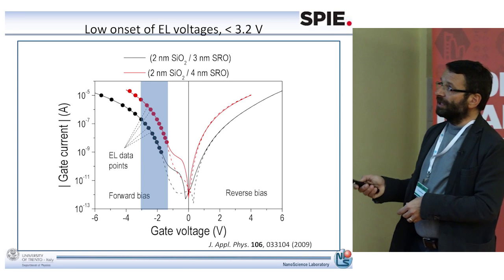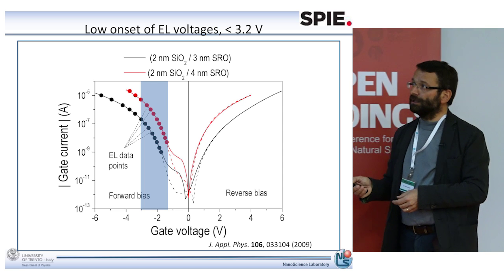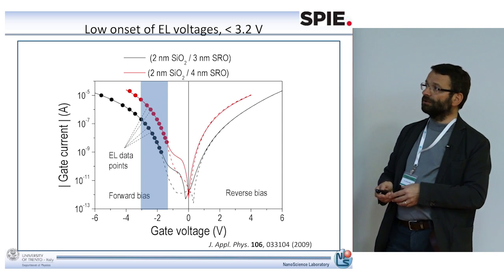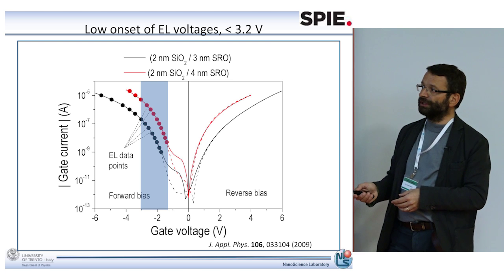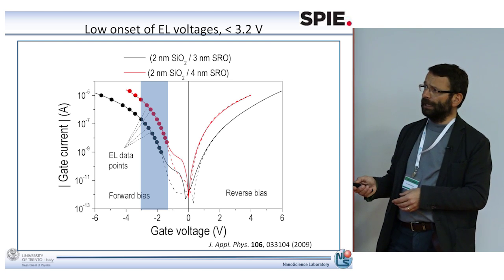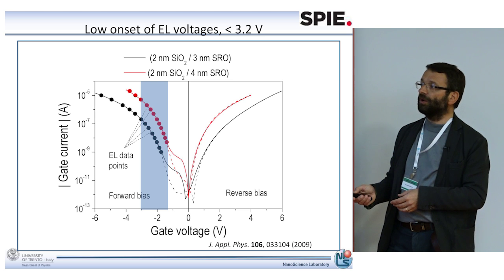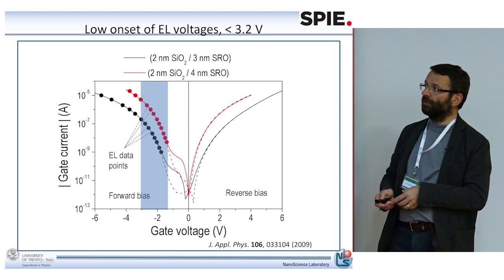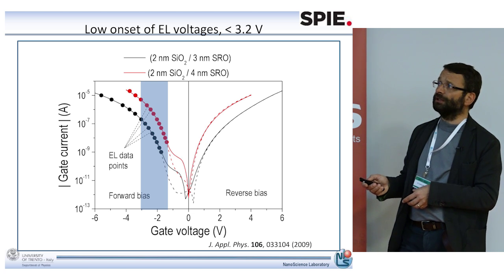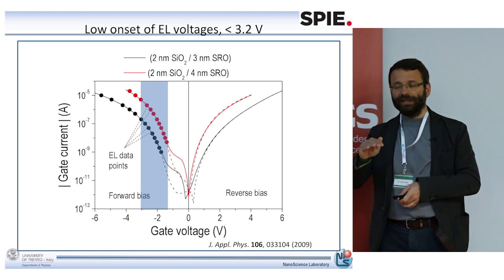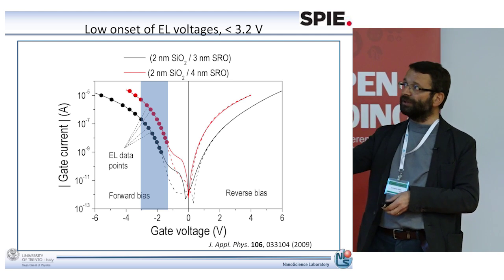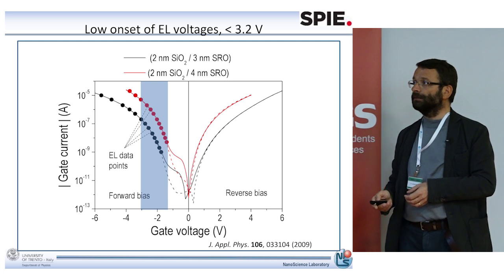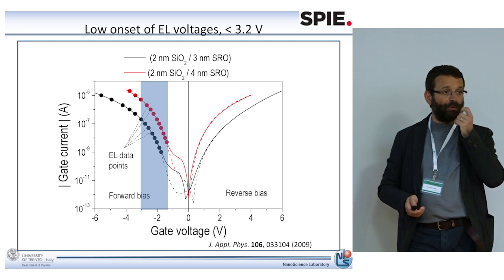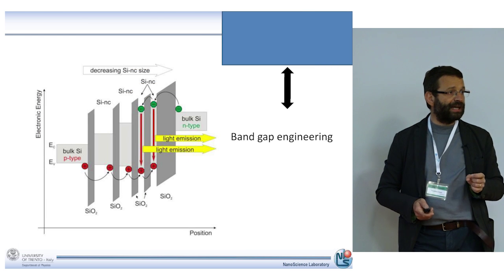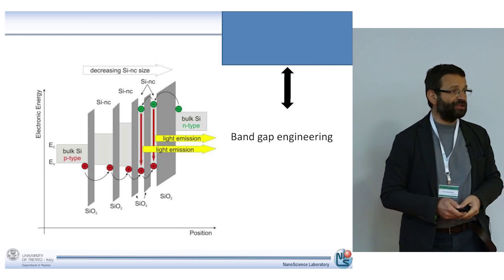So these are the IV characteristics, and the points are the electroluminescence data. What you observe here is that you get electroluminescence for very low gate voltage, so you apply a very small gate voltage. And what you also observe is the kind of accuracy that you need in the growth process. You have to make multi-layers of 2 nanometer silicon oxide and 3 nanometer silicon nanocrystal. But then we decide to play a little bit more with band gap engineering, with the control on the size, in order to improve even more the efficiency of the LED.